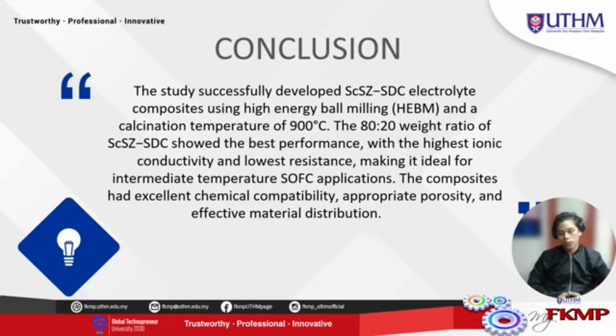The data collected from the porosity test and the EIS measurement show a clear relationship between porosity and electrochemical performance across the different compositions and temperatures. The EIS data indicate the compositions with the highest porosity, such as 70-30 and 80-20, generally exhibit lower resistance and higher conductivity, leading to lower ASR value. This finding highlights the critical role of the material microstructure in electrochemical performance, where higher porosity facilitates ionic transport by providing more pathways, thus reducing resistance and enhancing conductivity. Effective operation requires low resistance and high conductivity.